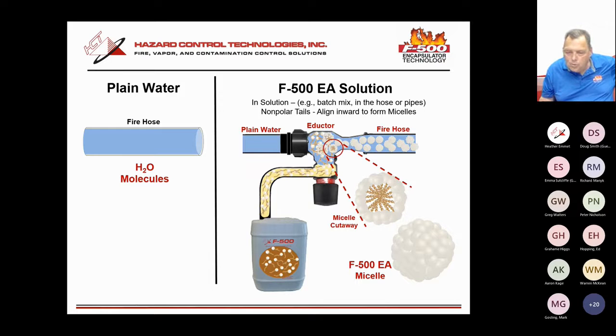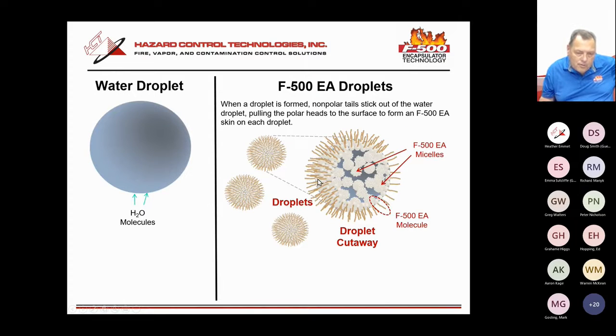And they exit the hose. What happens is the micelles closest to the surface break apart, and now we form a skin on the surface of every droplet. And inside, we still have hundreds of thousands, if not millions, of spherical micelles. So this is different than a wetting agent. A wetting agent doesn't have these spherical micelles. Obviously, a foam doesn't have them. We all know the basic building block of foam is a bubble, and we put hundreds and thousands of bubbles together to form a blanket, and we're mechanically separating the fuel from the oxygen to smother the fire.